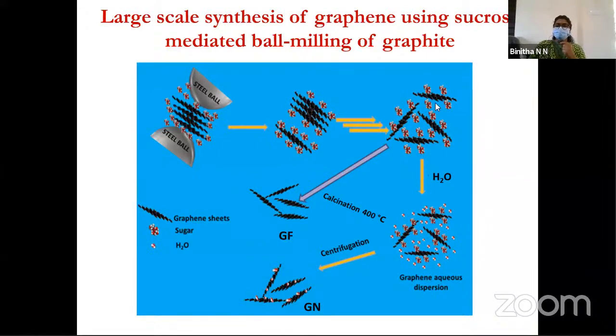In addition, we can mix the graphite milled mixture in water. We can disperse it in water by sonication, and the sucrose ball mill mixture is dispersible in water even without sonication. So aqueous processable graphene can also be produced by this route.